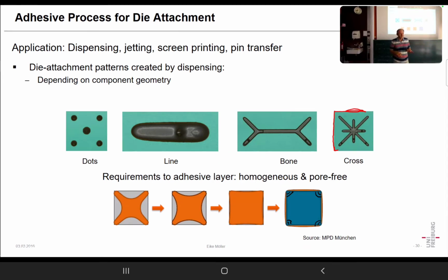The reason is, imagine you would print a ring, and put the chip on. You could be quite sure you have a pore inside that ring. So in the end, you must be sure that always in the middle you have most of the material, and when you put on the chip, the material is pressed to the outside in a way that no porosity can come into existence. That's a trick, and here we can see it.